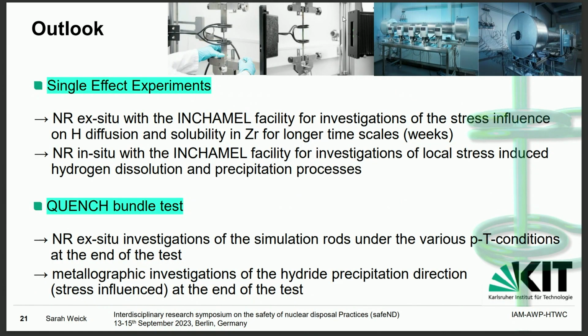So to give you a short outlook, we will continue single effect experiments, doing neutron radiography ex situ with the INCHAMEL facility, for investigations of the stress influence on hydrogen diffusion and solubility over much longer timescales than we did before. Also, we will repeat these samples to investigate the local stress-induced hydrogen dissolution and precipitation processes. Then we will try to get all information possible out of the quench bundle test at the end, also with neutron radiography experiments and then metallographic investigations as well.